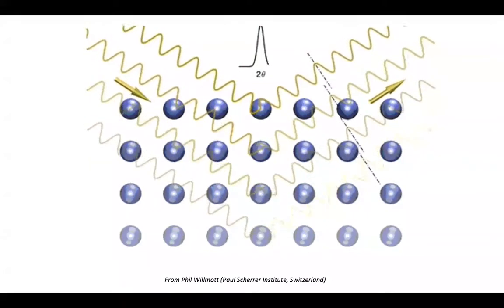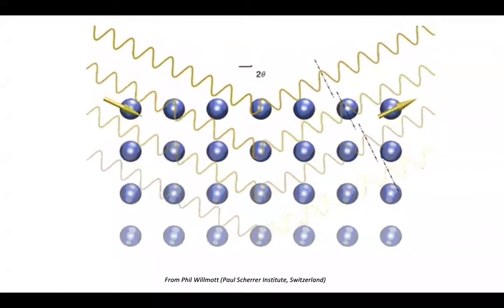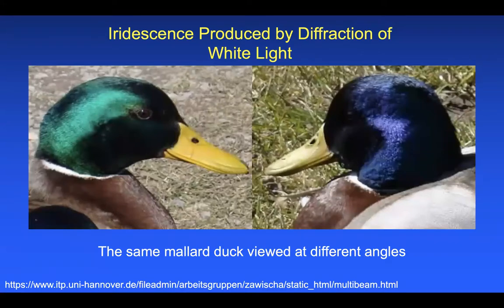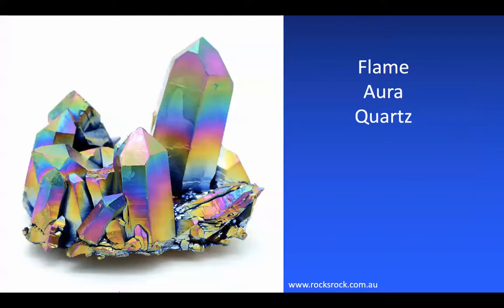And so this is really underlying the basis for structural color. We can see the dependence of that scattering angle in these 2 photographs of the same mallard duck at different angles. So on the left, the head looks green to us, and on the right, it looks blue. The blue is at a lower angle, and so we're seeing selective total constructive interference of the shorter blue wavelengths, but at a higher angle, it's the green wavelengths that interfere totally in a constructive fashion.